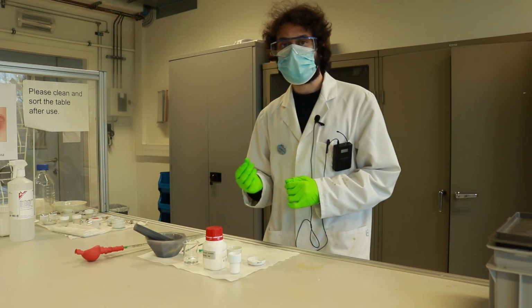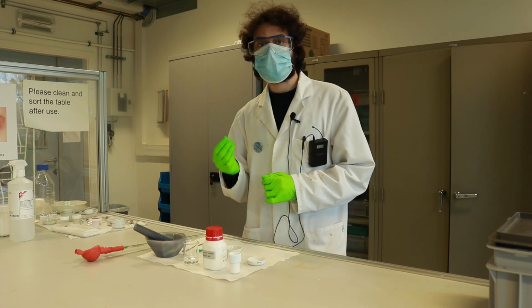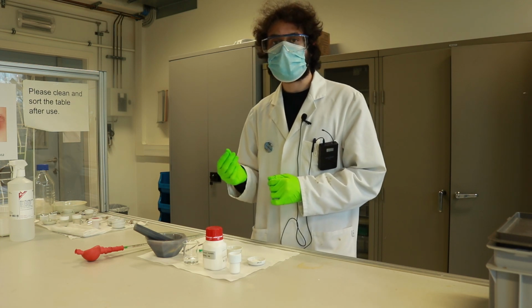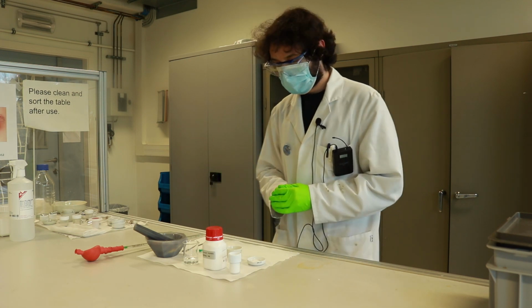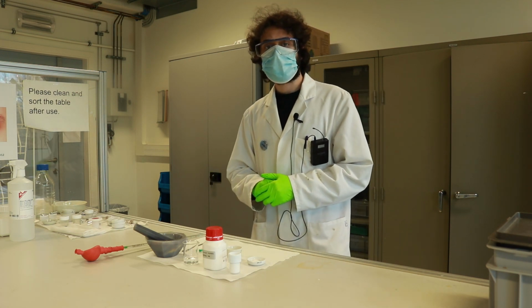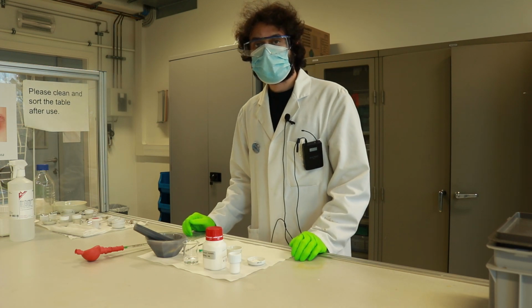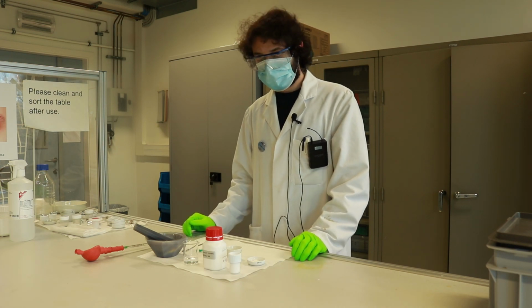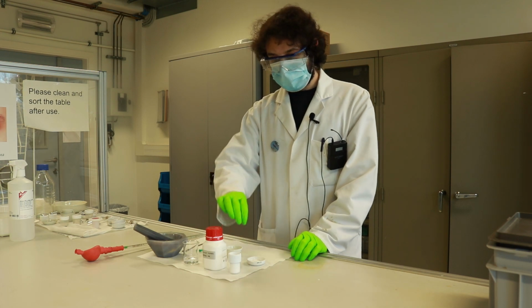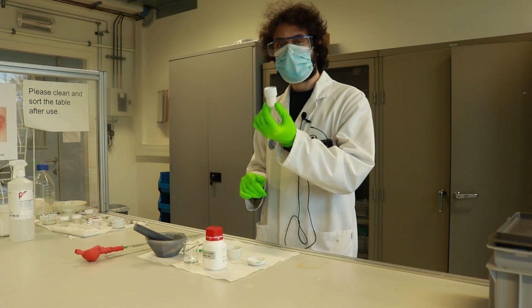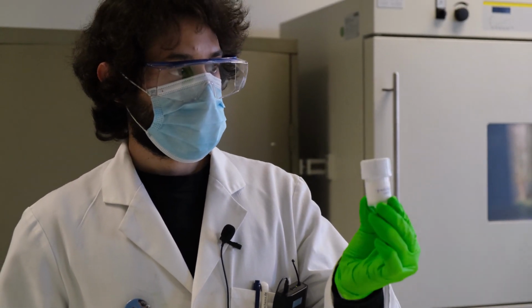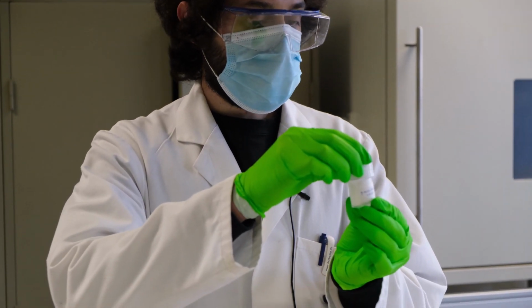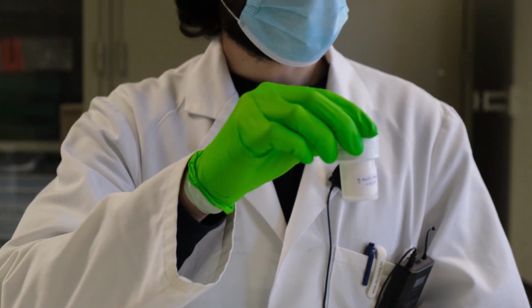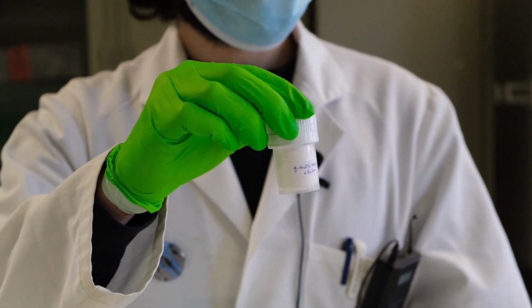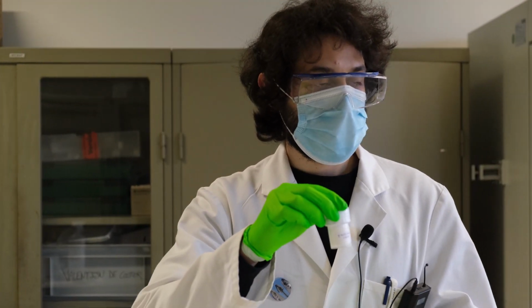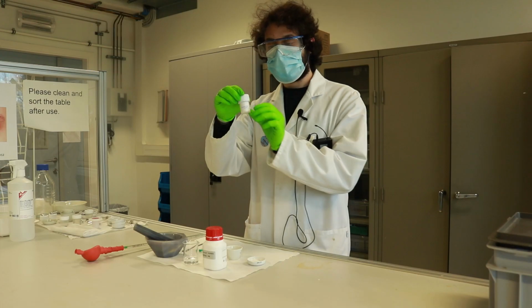That is the carrier of your active metal or your active species that will catalyze the reaction. In this case, today I'm going to be preparing a nickel catalyst that is supported on gamma alumina. So the support in this case is gamma alumina. It's a white powder. And I have made sure that I have crushed this support into fine powder. This will limit mass transfer during the synthesis procedure.